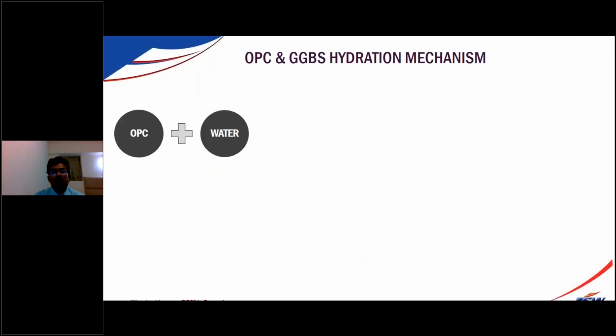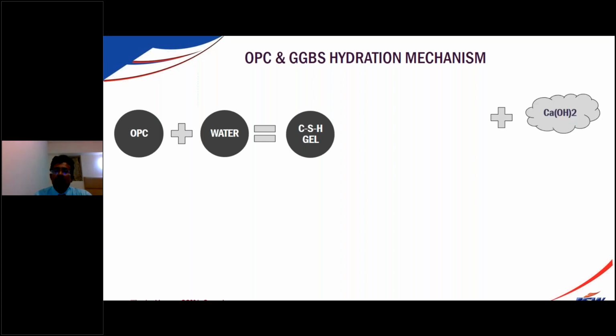So looking at the mechanism, how the GGBS is going to help us is like this. When we make OPC cement, we add water, and we get calcium silicate hydrate gel. So what will happen? We are going to get calcium hydroxide and CSH gel. The calcium hydroxide is a very unstable product, which is like cholesterol in the concrete. If we have cholesterol, we have to remove it. We need to remove the calcium hydroxide as much as possible from the concrete matrix.